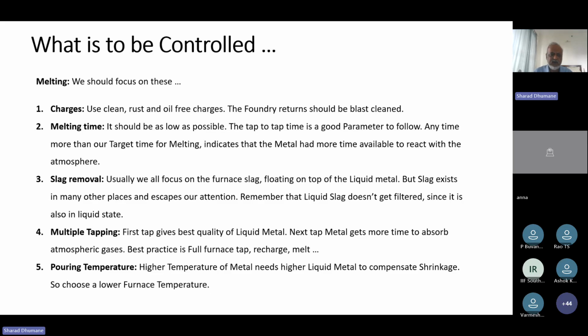Lastly, pouring temperature. The higher the pouring temperature, the higher will be the solubility, and the liquid slag formation. So as far as possible, tap at a temperature which is optimum. If you want a certain temperature, okay, go for it, take care, but exercise control so that you don't cross it.